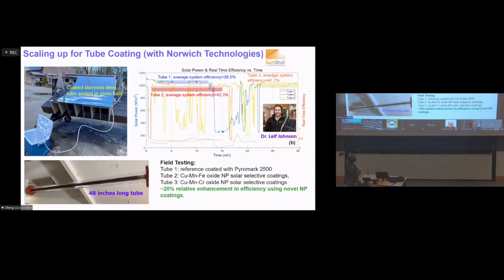As you remember, with chrome, we should be able to get slightly better performance than iron. And okay, this is White River Junction. You can see the solar illumination versus time, and the clouds coming in. So you have to find a region, a time scale, where the curve is relatively flat and compare the efficiency. And indeed, you see about 20% improvement in efficiency with our copper manganese chrome oxide nanoparticle coatings.